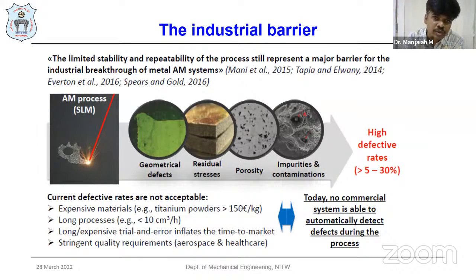To have a breakthrough in these things, a lot of research and development is required to understand the constraints or barriers with respect to these kinds of 3D printing processes. If you see, geometrical defects may be there, residual stresses may be there, porosities, as well as impurities and contaminations. You can see the geometrical defects in terms of the layer depositions, where maybe one surface is very high compared to the other surface because of improper solidification and cooling, and the residual stresses because of the repetitive melting, and the porosities, as well as the impurities, some contamination of foreign particles.